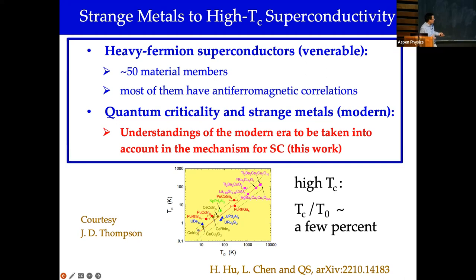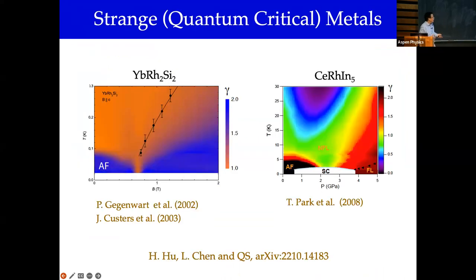And in addition, above the superconducting transition temperature, if you look at the physical properties, that's where the strange metallicity comes in. If you have quasiparticles satisfying Fermi statistics, the existence of the Fermi surface makes the scattering rate extremely reduced. In fact, as a result, the scattering rate would depend on temperature in a T-squared fashion.